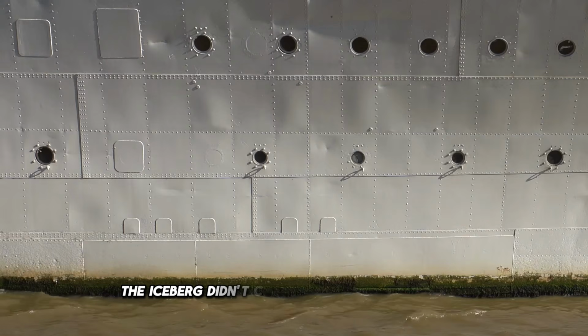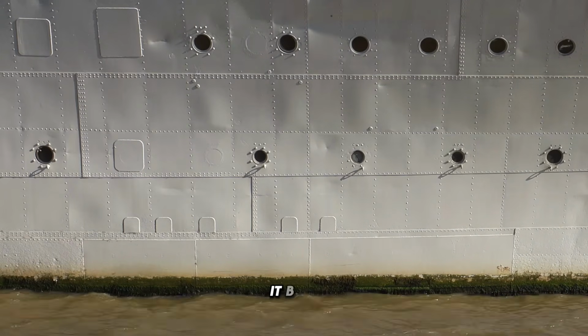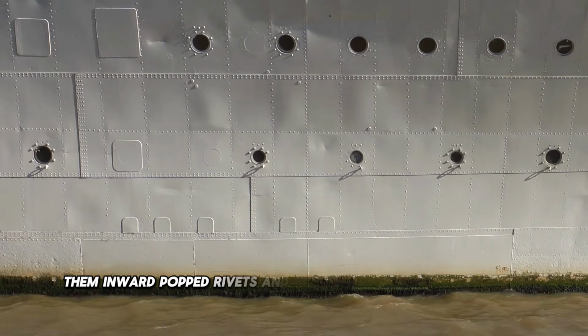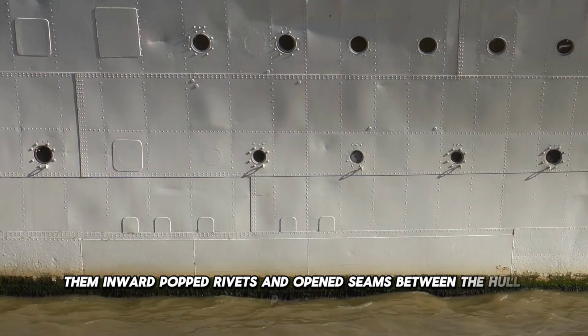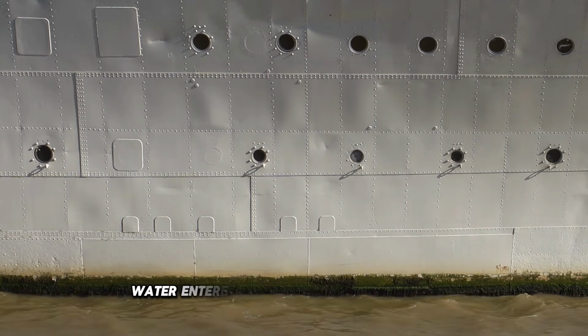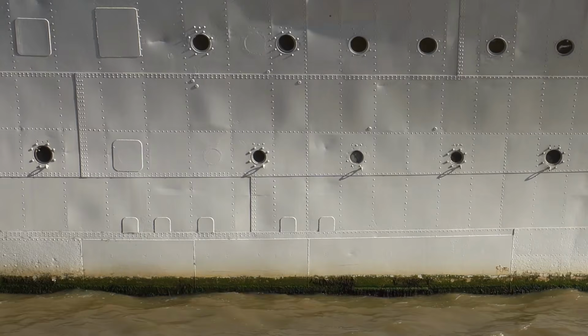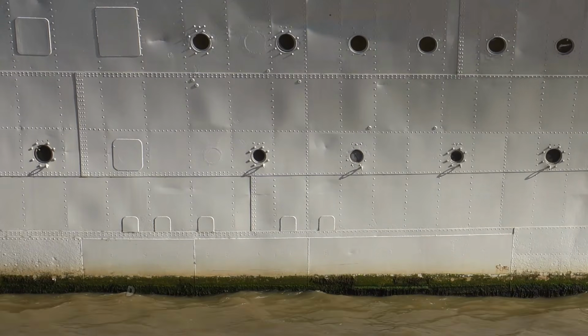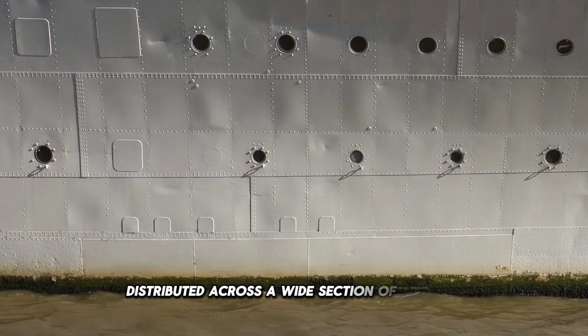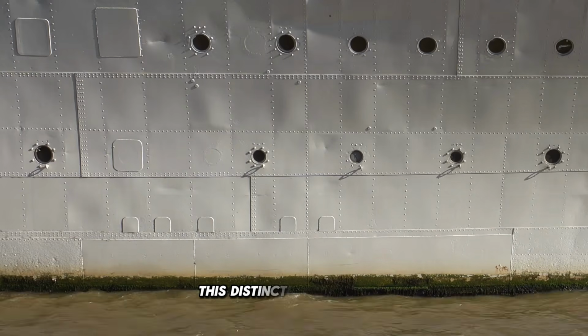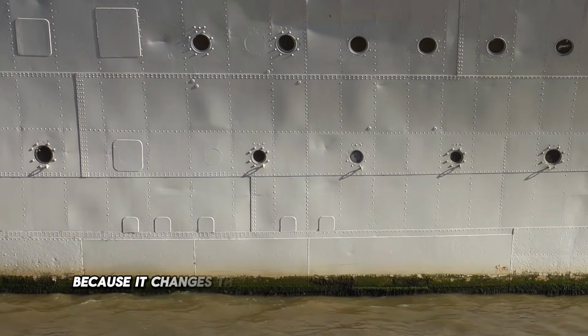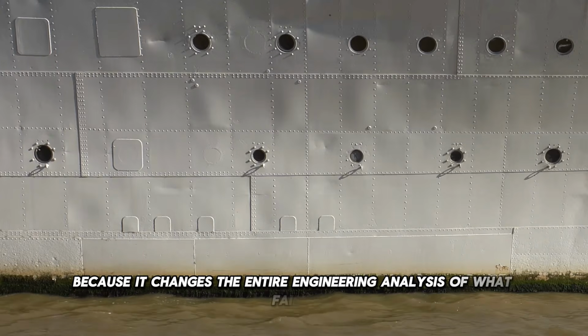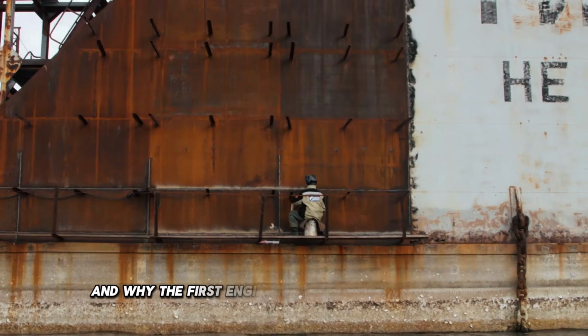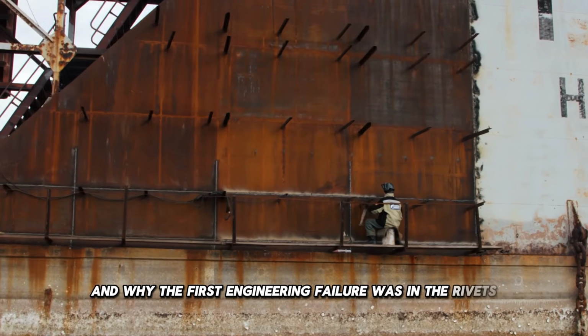The iceberg didn't cut through the steel plates. It bent them inward, popped rivets, and opened seams between the hull plates. Water entered not through a dramatic tear, but through multiple small gaps distributed across a wide section of the hull. This distinction is critical because it changes the entire engineering analysis of what failed and why. The first engineering failure was in the rivets.